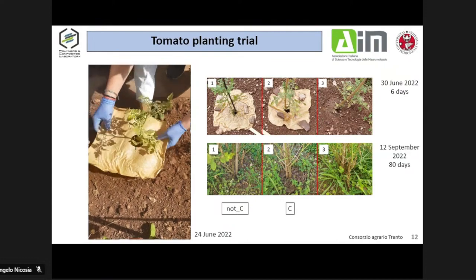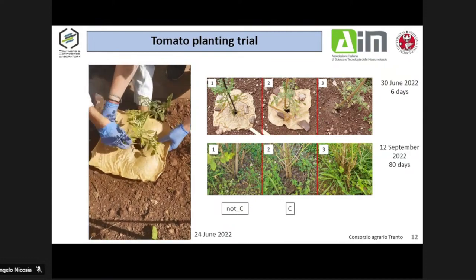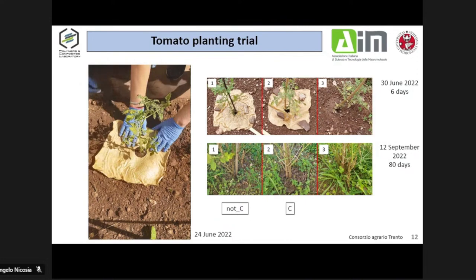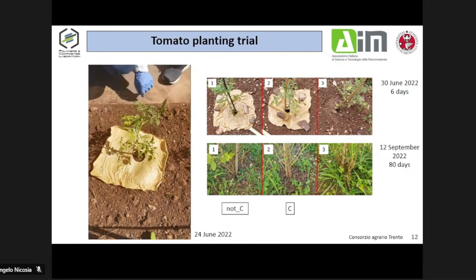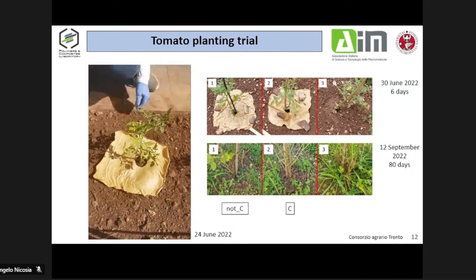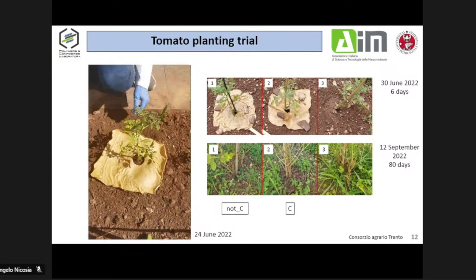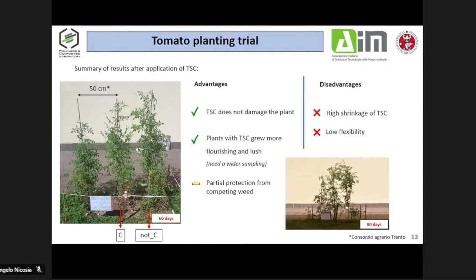But the most important thing is that after 80 days, in the case of the non-cross-linked material, so without thermal treatment, the material dissolved and degraded. Instead, in the other case, we have a better response, an increase in durability, and a partial protection from weeds, compared to the other two cases. So to summarize the results, the plants with the topsoil cover grew better.